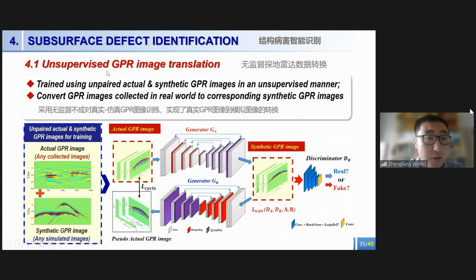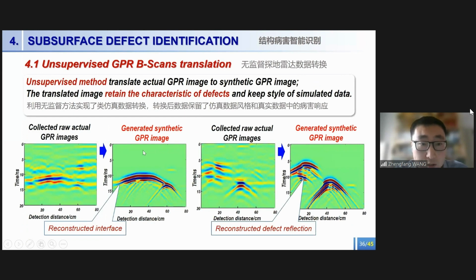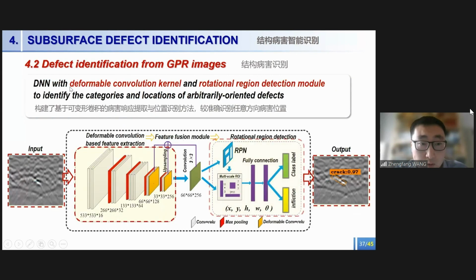To be specific, the unsupervised GPR image translation network is trained using unpaired actual and synthetic GPR data in an unsupervised manner. And this can convert the GPR image collected in the real world to the corresponding synthetic GPR image. Then the translated synthetic GPR image retains the characteristics of the defects and keeps the style of simulated data. This is followed by a DNN model with a deformable convolutional kernel and a rotational region detection module to identify the category and location of arbitrarily oriented defects.